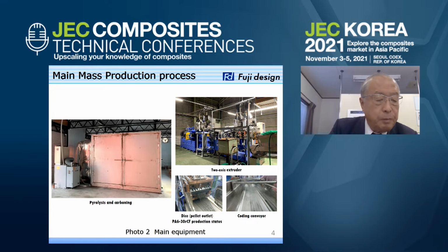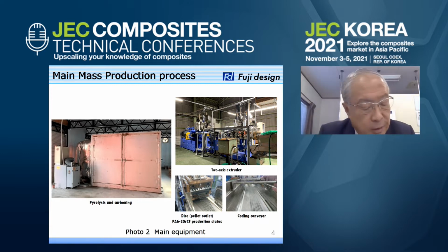CFRP or CF prepreg in the furnace is heated from 300 degrees C to 480 degrees C to carbonize and leave residual amorphous carbon content. Residual amorphous carbon comes from the matrix thermoset resin, for example, epoxy. This residual amorphous carbon content is controlled at 3 to 5 weight% to work as sizing material for the carbon fiber. We found this sizing effect is a very new issue because we have no need to put sizing materials onto the recycled carbon fiber.